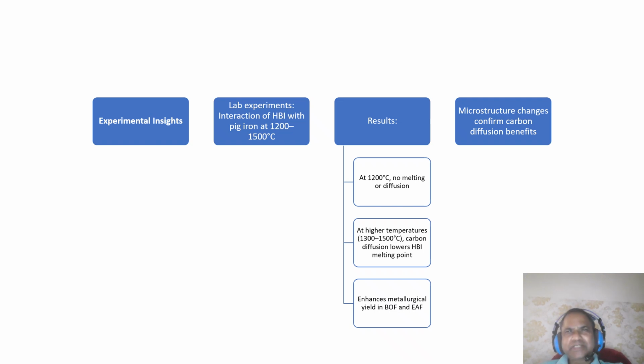Now coming to the laboratory experiment, which explored how HBI interacts with pig iron at temperatures from 1200 to 1500 degrees centigrade. At 1200 degrees centigrade, no melting or diffusion occurred, but at higher temperatures, carbon diffusion lowered HBI's melting point, enhancing the metallurgical yield in both basic oxygen and electric arc furnaces. Microstructure analysis confirmed these benefits, also highlighting the role of carbon diffusion. So altogether, all these give an advantage.